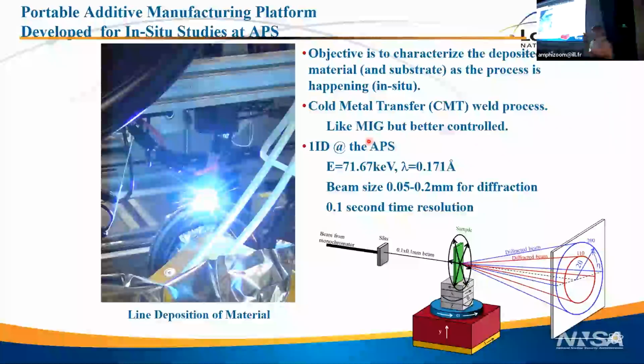In fact, we had something like a 10 times reduction in the beam to prevent the pixels from saturating. So this was fully set by the GE detectors that they use at the APS. I understand Eiger's now running at 500 hertz and could do this measurement at that rate.